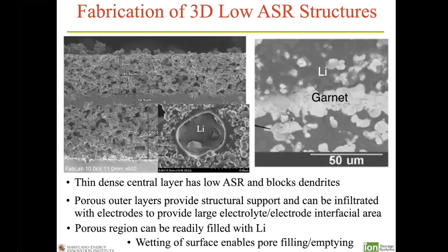Because we wet the surface, you can see how the lithium actually prefers to touch the garnet surface versus itself. And so this enables us to cycle this lithium metal back and forth by a pore filling and emptying mechanism, removing that issue of infinite volume expansion that you would have if you had a lithium foil for your anode.